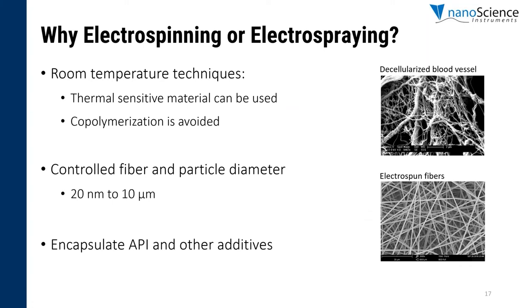But now, why are researchers and industries using the electrospinning and electrospraying techniques? Both techniques can process fibers or particles at room temperature, which makes them suitable for the use of thermally sensitive components. Another advantage is that fiber and particle diameter can be tailored to application needs. Typical control values range from 20 nanometers to 10 micrometers, or even more if you do the proper solution optimization.